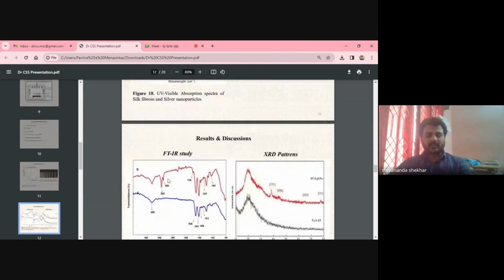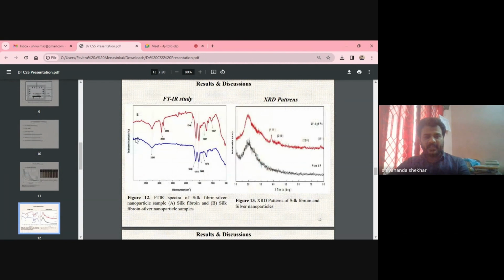Next, FTIR spectra. Here, figure 12A is the pure silk fibroin graph, and B is the silk fibroin silver nanoparticle composite solution. See here the absorption bands observed at 1536 and 1514, corresponding to the amide groups present in the silk fibroin. And the band around 3280 is due to the hydroxyl group present in the silk fibroin. There is also a difference in the peaks: one extra peak arises at 1746.